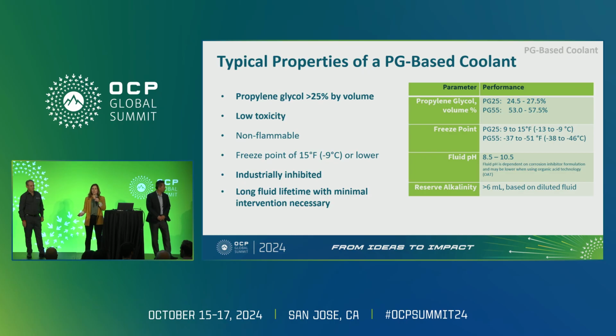Okay, so what can you expect for typical properties of a PG-based coolant? Biggest thing is it's going to contain greater than 25% propylene glycol by volume. The reason that this is important is because anything 25% and greater is considered biostatic, meaning there would be very minimal risk of biocontamination. Next, PG-based fluids should be low toxicity, non-flammable.